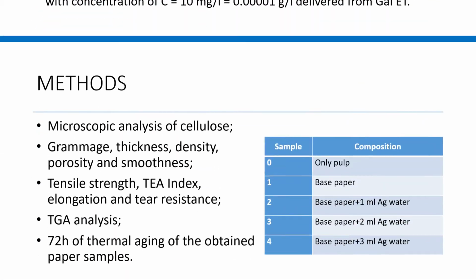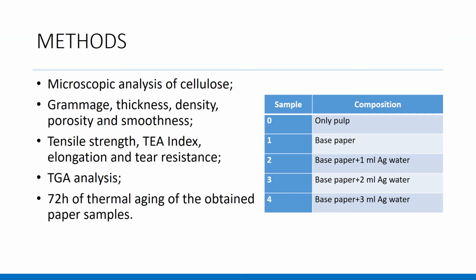liter. The main methods used in this work were defining the type of the cellulose used with a microscopic analysis, grammage, thickness, density, porosity, and smoothness determination, tensile strength, TEA Index, elongation, and tear resistance, TGA analysis, and color coordinates measured every 6 hours during the 72 hours of thermal aging of the obtained paper samples.